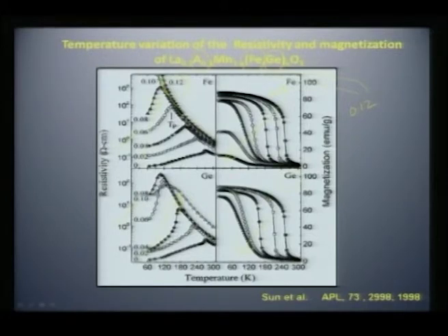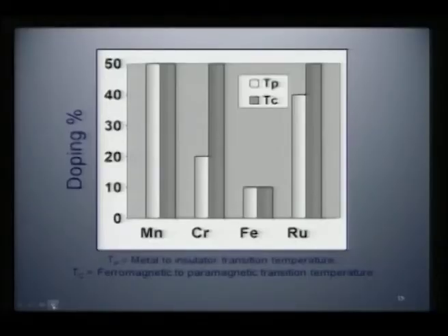So, even in this case you can see that it happens at 10% of germanium. So, you have either 12% of iron or 10% of germanium totally killing the ferromagnetism and the metal insulator transition. In the next graph I will show you other transition metals.